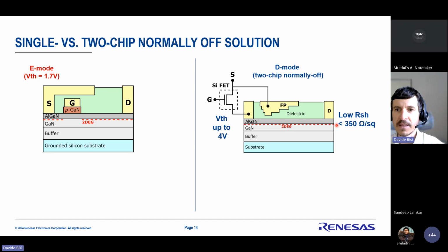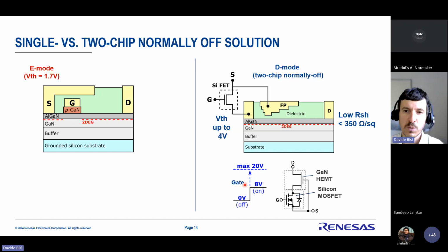A few things to say: the channel resistance can be lower than 350 ohms per square, so we can really optimize the channel resistance because it's not connected to threshold. So threshold and resistance are separate, so we can tune them separately, which is a very good feature of the cascode architecture. And as we know, a very robust gate: it's off at 0 volt, we turn it on at 8 volts, and then there's plenty of headroom up to 20 volts for robustness and reliability.